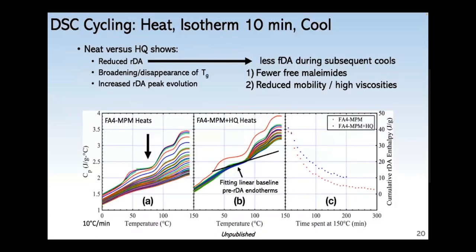The last way I tried to study the maleimide self-reaction is through a DSC cycling procedure where I heated the Fa4 material up to 150 C, isothermed for 10 minutes, and then cooled down repeatedly. And I show the results for that in plot A with heat capacity against temperature.